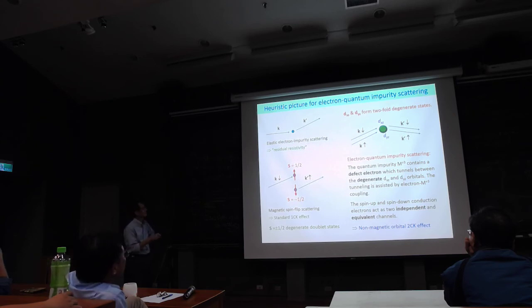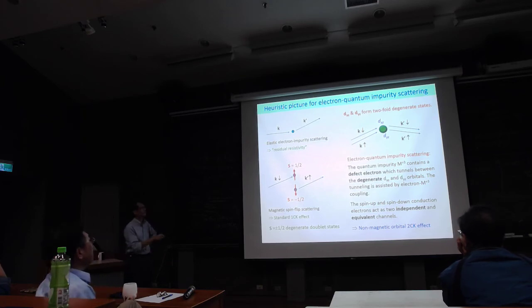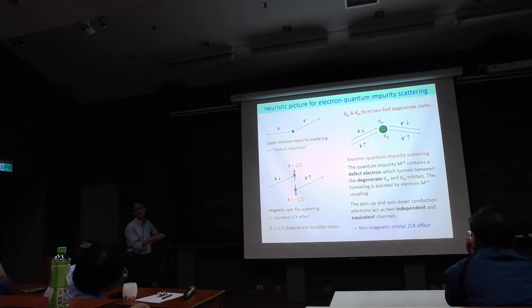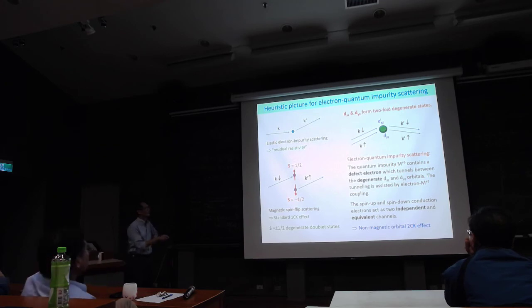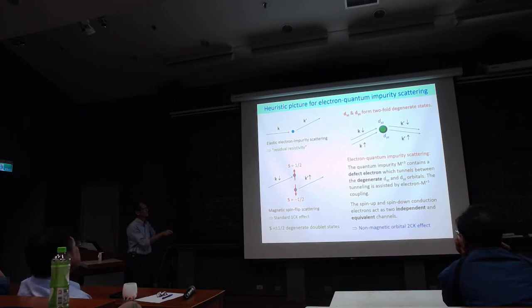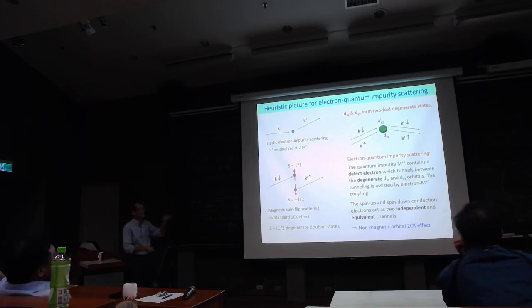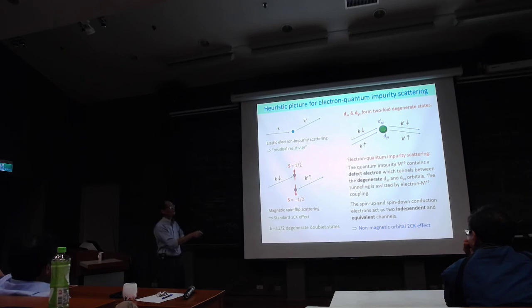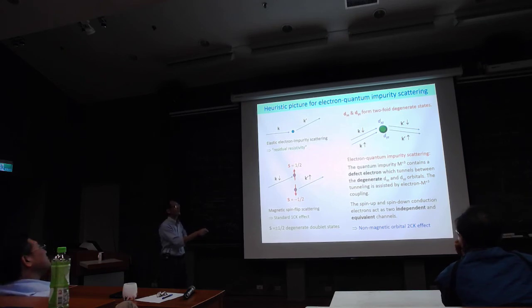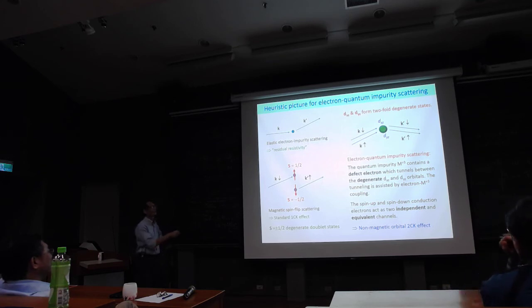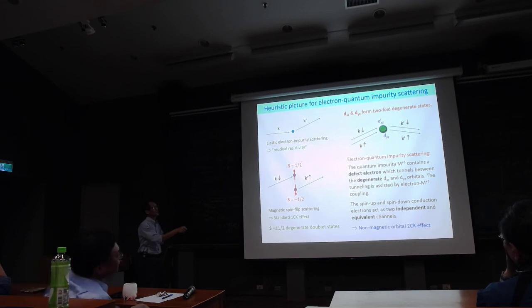Just to remind students, if you have a static defect in a real metal or solid, you have a scattering and then a residual resistivity. If you have a magnetic defect, then you have a standard Kondo effect. So before and after scattering, the impurity spin flips directions. In our case, we have no spin. Our scattering center can take either dxz or dyz orbital, and these two orbitals are degenerate. And so our spin down conduction electrons, together with spin up conduction electrons, also try to screen it, and they compete.